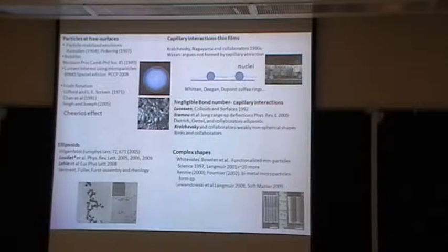And this argument came up again in very beautiful papers from Chicago, where people were looking at evaporating drops that contained colloidal particles. What they saw was that as the evaporating drop proceeded, there was a collection of particles that accumulated near the three-phase contact line. The ideas were that evaporation near the contact line is fast compared to elsewhere on the drop.